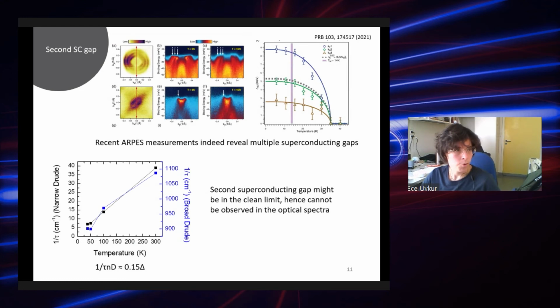Okay, so the second superconducting gap, we were curious about that, and indeed the recent ARPES measurements reveal multiple superconducting gaps, and we catch this one here very nicely. This one is out of our measurement range anyway, but you see that there is a second gap over here around 9 millielectronvolt, which would put you in a strong coupling limit, basically.